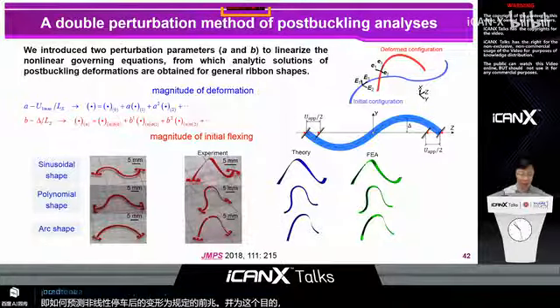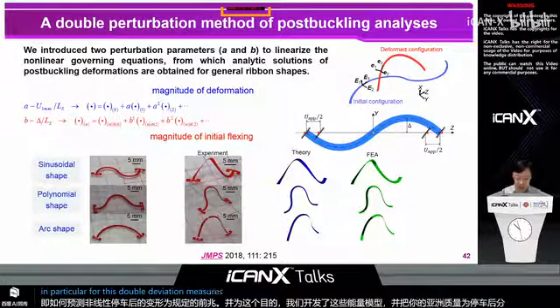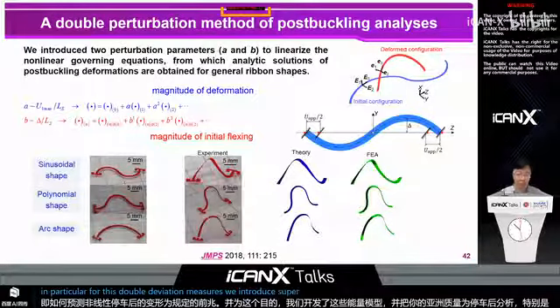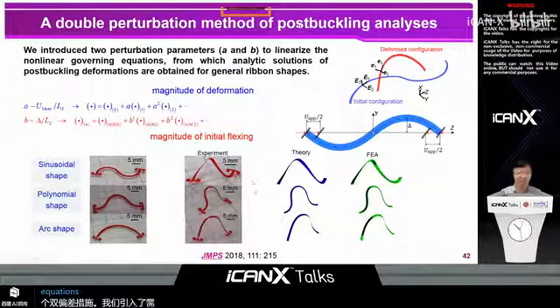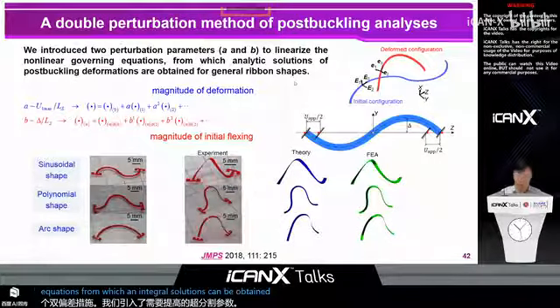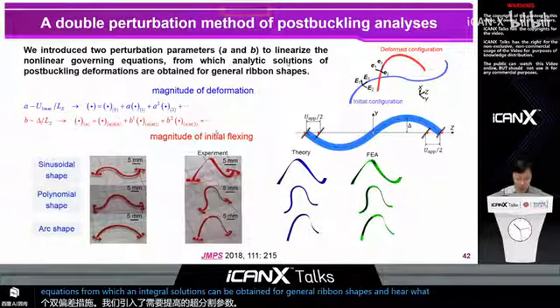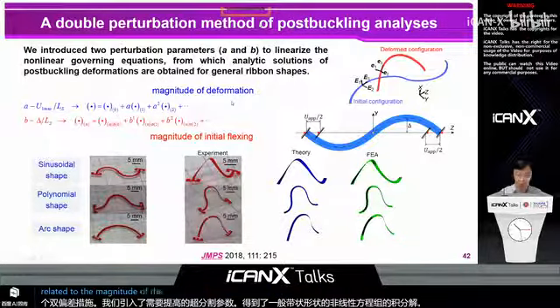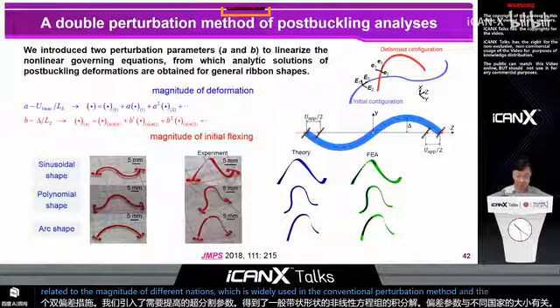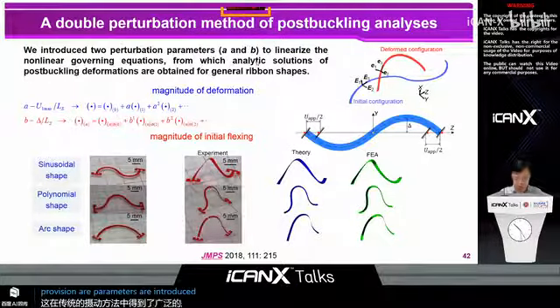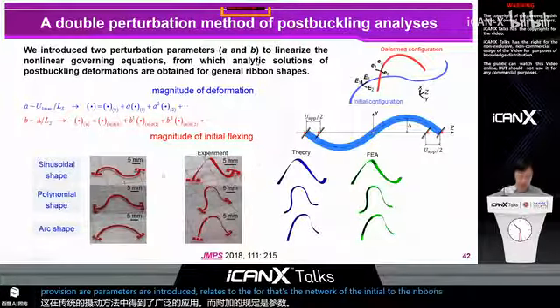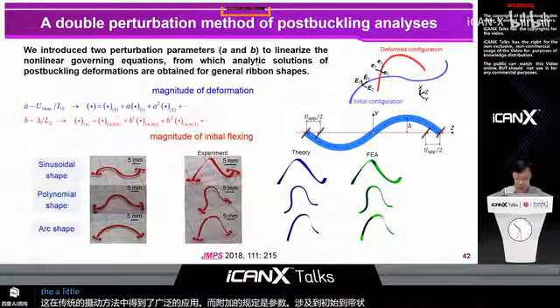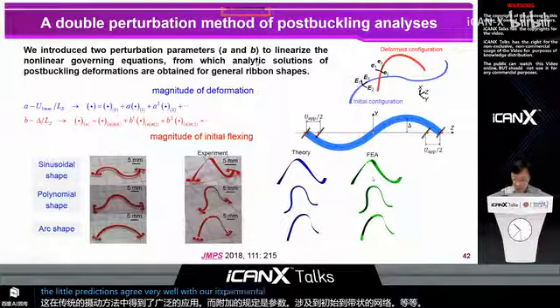In particular, for this double perturbation method, we introduce two perturbation parameters to linearize the nonlinear governing equations from which analytical solutions can be obtained for general ribbon shapes. And here, one of the perturbation parameters is related to the magnitude of deformation, which is widely used in the conventional perturbation method. And the additional perturbation parameter we introduced relates to the flexing level of the initial 2D ribbons. And as you can see here, the analytical predictions agree very well with our experimental results and simulation results.